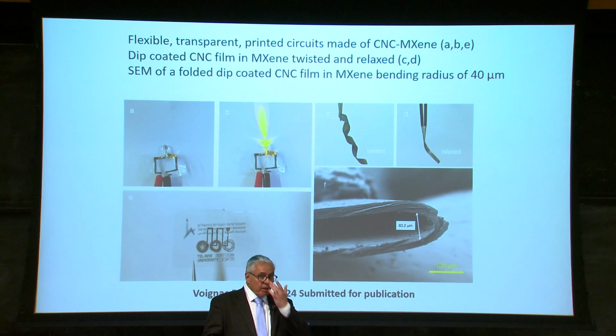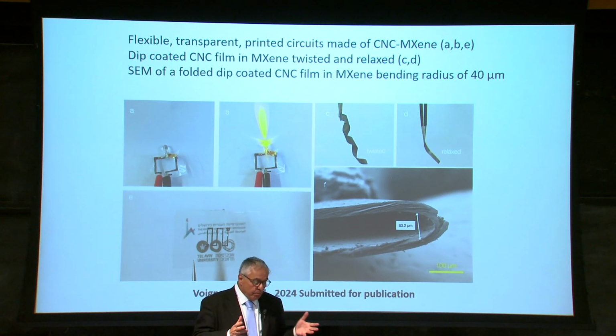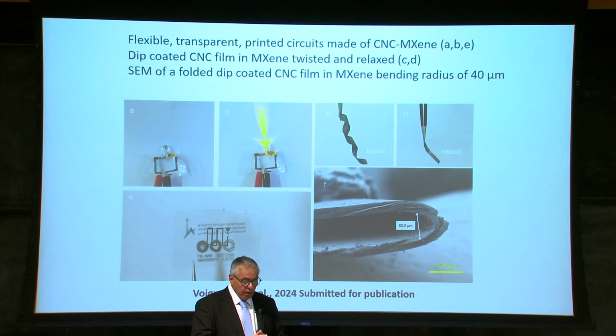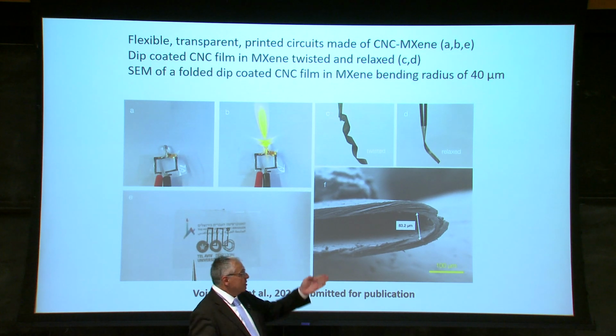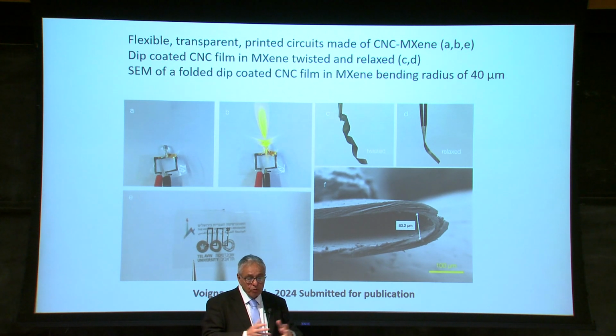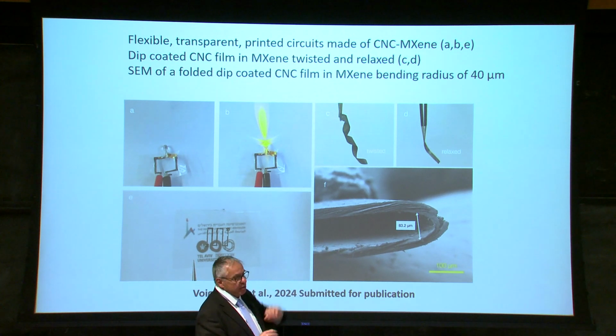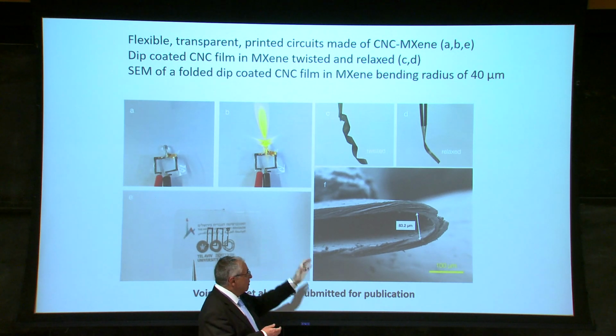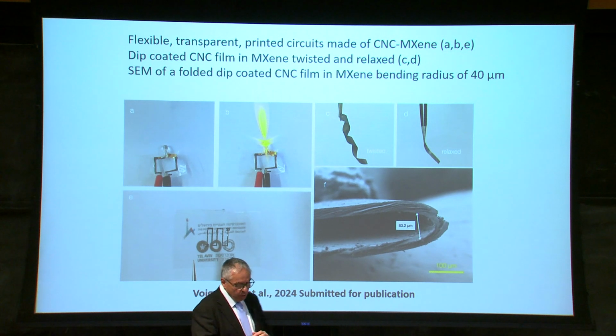So what else can we do with these materials? We can make flexible, transparent, printed circuits which are made of CNC MXene, dip-coated CNC films in MXene, twisted and relaxed, and also foldable materials. You can see here we've been able to fold it into a diameter of close to 40 micron. Admittedly, on the right-hand side, you can see that some of the coating is starting to fail, but I think that these are quite impressive data.